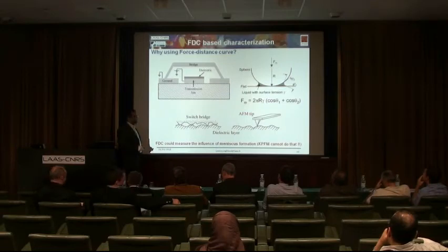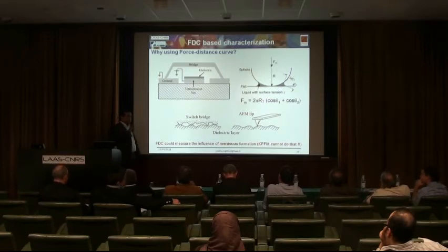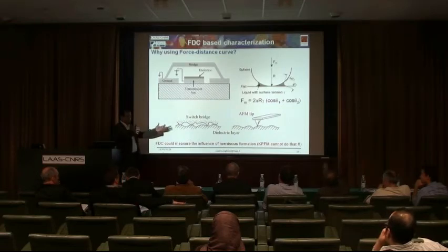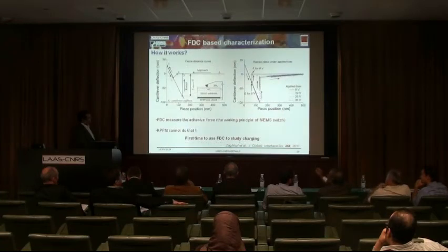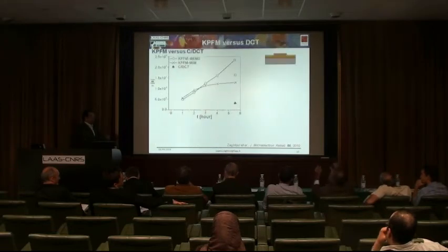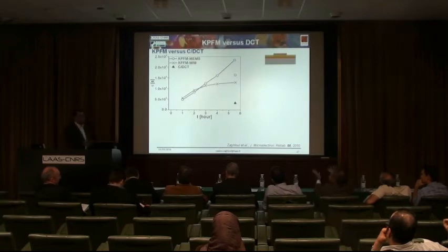Okay. This is a simplistic cartoon of a single asperity contact. Although at the bottom we claim there's a single asperity contact, when you look at the tip of the tip, you have these nanoasperities. So what is really happening is you're making multi-menisci. As you increase the liquid, we have more of this nano roughness present on the tip, creating the meniscus bridges. So within a single asperity contact, you have multiple asperity contacts, and that's really what increases it.